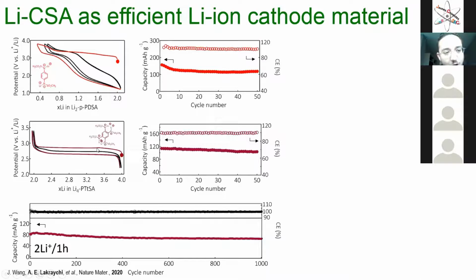Then for the other molecule, if you add additional sulfonamide groups, you will have a perfect redox reaction with a perfect electrochemical behavior. We have exactly 2 electrons, low polarization, and the potential is a little bit lower, 2.7, 2.8, because the additional sulfonamides act as electron donors and will lower the potential. But thanks to this, you will have additional good stability. You can compare this one below with the one above. The one above has a slight capacity loss, but this one has a straight line.